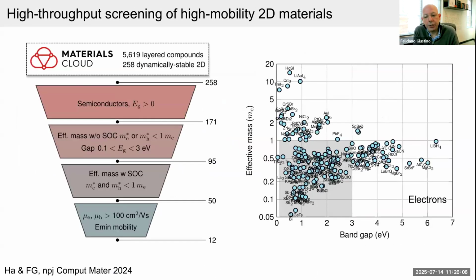So based on that, what we need is to try and screen large materials databases to potentially identify 2D materials with high mobility. And in this field, there have been several databases put forward by the community. So we chose to start with the one put out by the group of Marzari at EPFL Lausanne, where they identified about 5,000 materials that can be exfoliated. And then out of that, we applied a hierarchical high-throughput screening approach, where you start performing simple calculations for all of the materials. And then you use this simple calculation to narrow down the list of candidates.